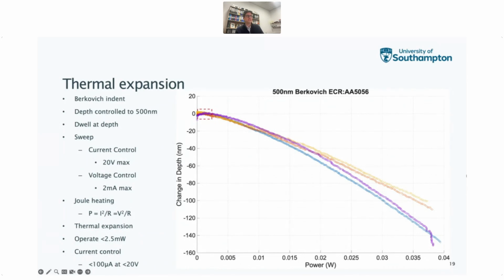And what I've done is plot the delta of the change in depth at 500 nanometers. And you see as you go higher in power, you are getting the tip effectively pushed out of the surface, because you're getting thermal expansion at the surface. This is pushing the tip away from where it was originally at 500 nanometers. So if you want to avoid this, you really need to be down here in this little red box, where you're not putting very much power in at all, to avoid any thermal expansion. In this case, we're trying to operate below 2.5 milliwatts of power dissipation within the ohmic contact. So in current control mode, that means something around less than 100 microamps at 20 volts floating voltage.